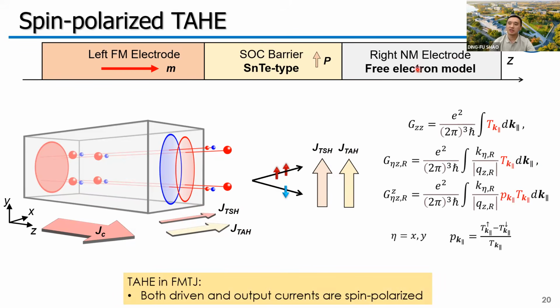If we consider the electrodes to have a free electron model, we can write down the formulas to calculate the longitudinal conductance, the tunneling anomalous Hall conductance and the tunneling spin Hall conductance. Here, T is the momentum-dependent transmission, and P is the spin polarization of the transmission. So obviously, according to these two formulas, if we have some unbalanced distribution of T or PT, we may expect a large tunneling spin Hall effect or tunneling anomalous Hall effect.